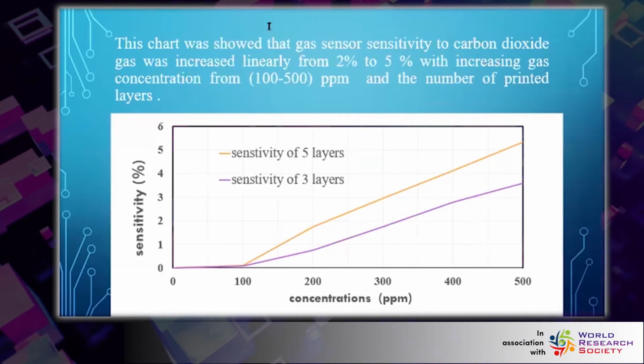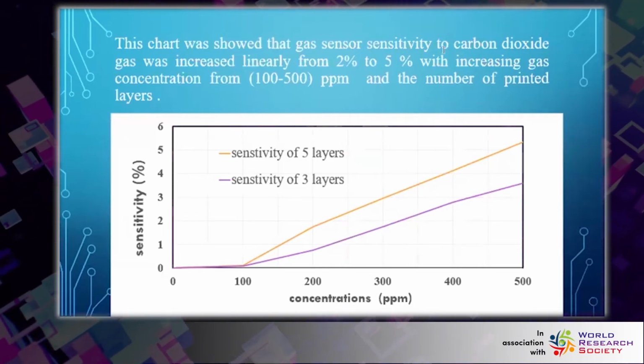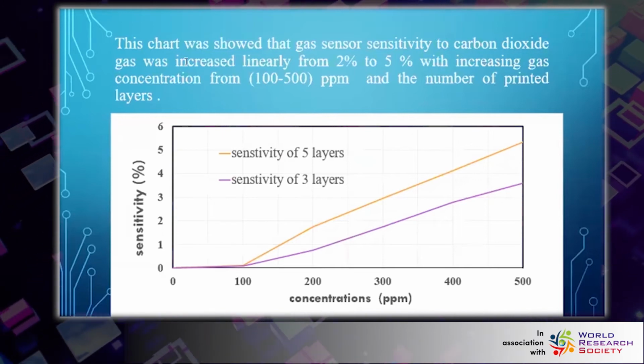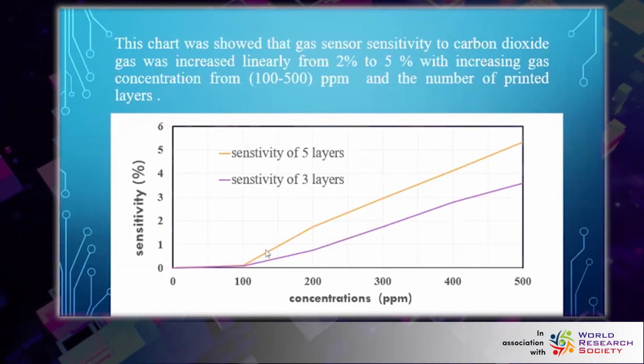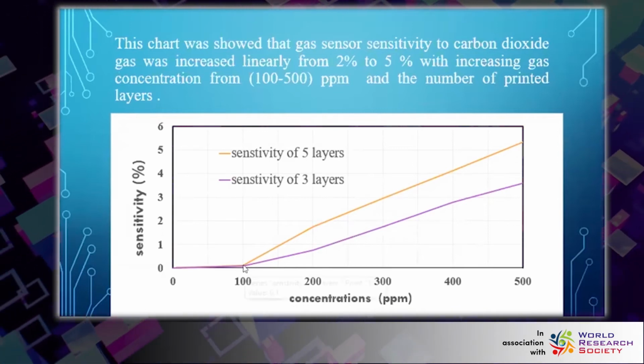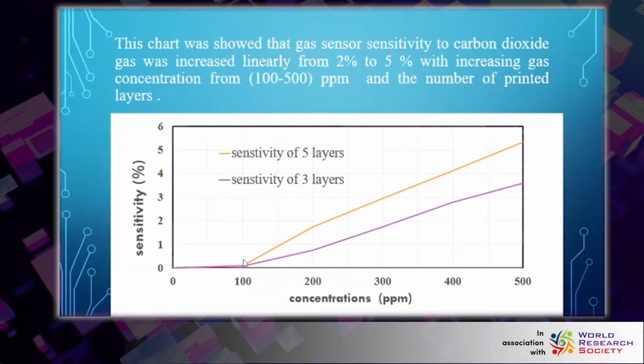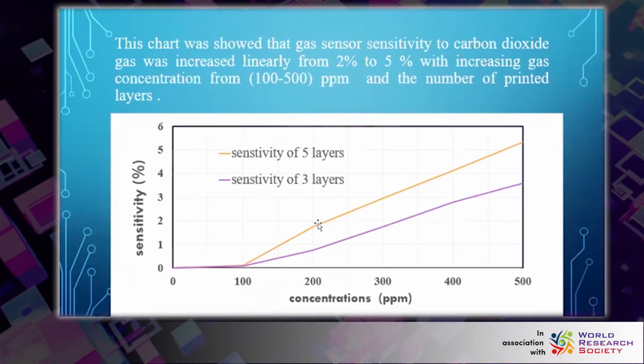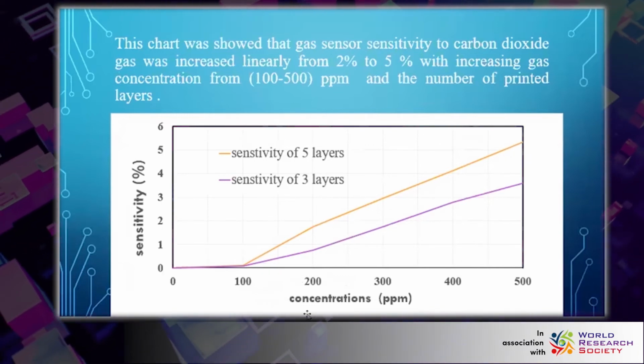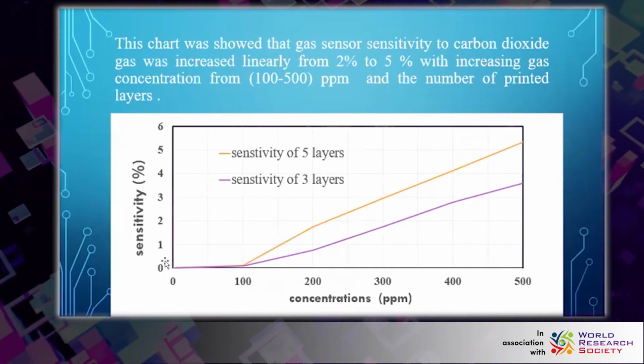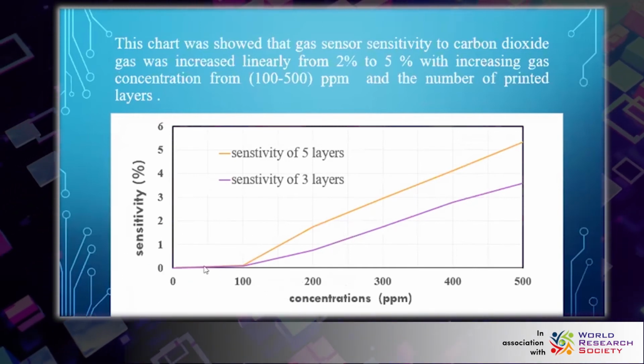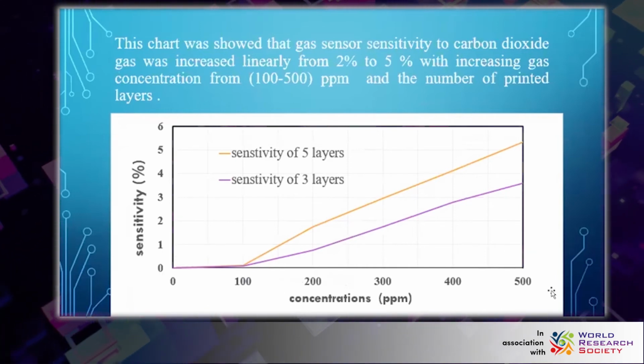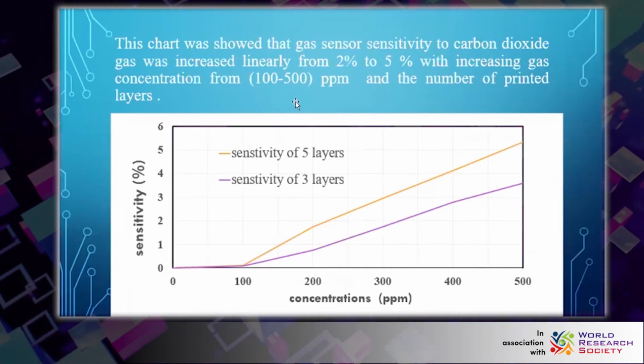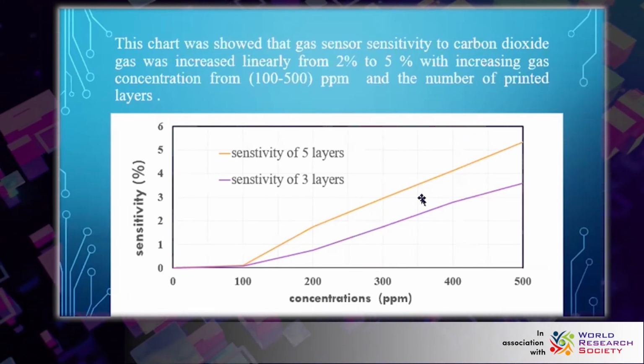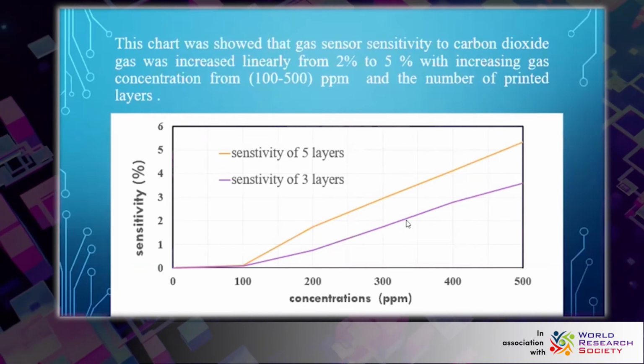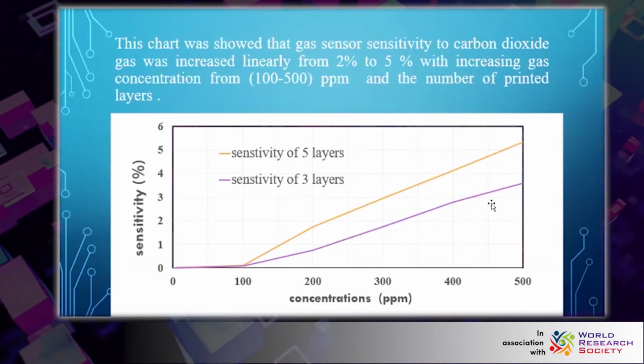This chart shows that the gas sensor sensitivity to carbon dioxide increased linearly. The sensitivity increased linearly from 1 or 2% to 5% when I increased the concentration from 100 ppm to 500 ppm of carbon dioxide. There are 2 lines. The first one is the sensitivity of 5 layers. The second one is the sensitivity of 3 layers.